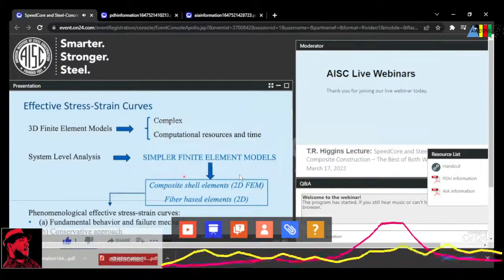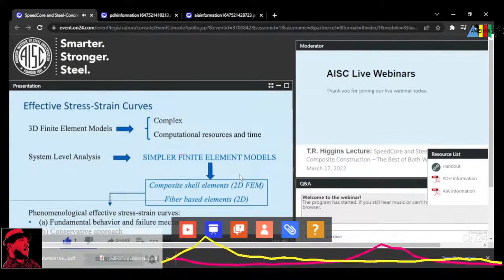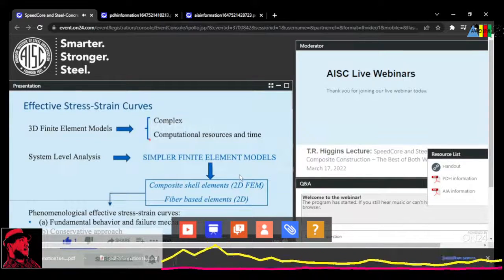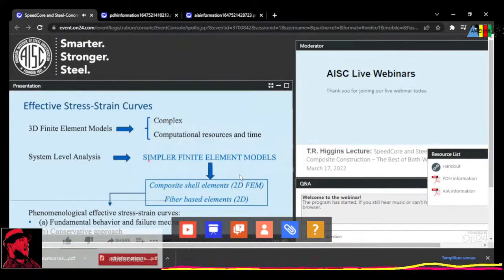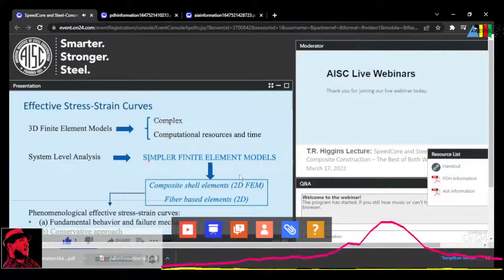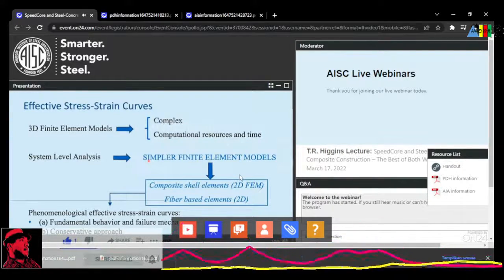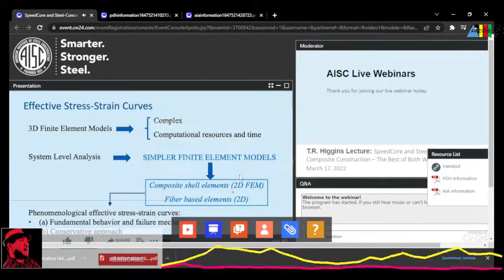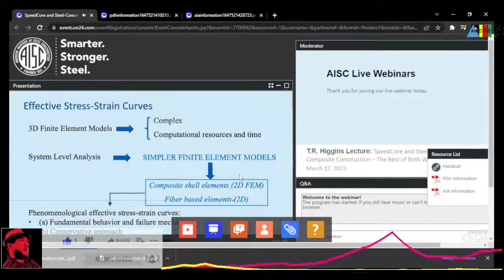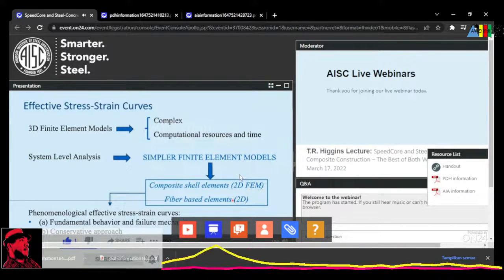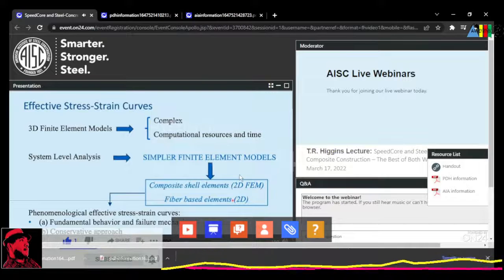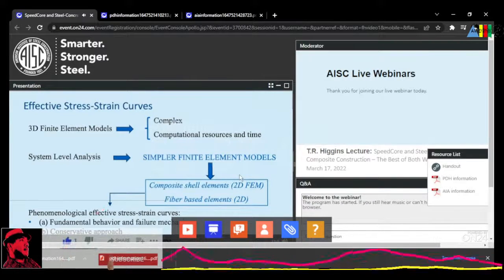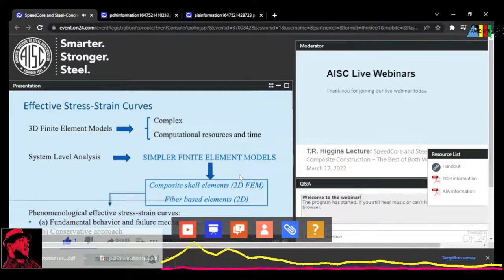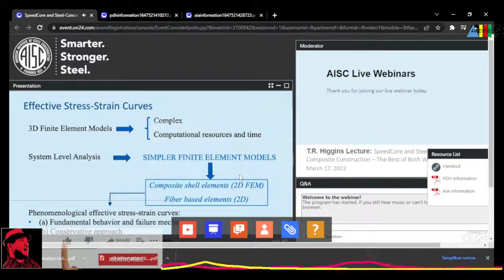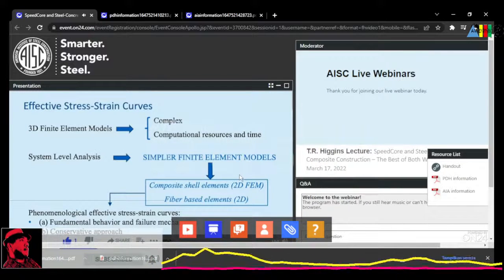However, the 3D finite element models are quite complex and time-consuming. They are good for evaluating local specimen behavior and failure. However, for system-level analysis, we need simpler 2D finite element models made from layered composite shell elements or 2D fiber element models. Both of these, however, cannot model some aspects of behavior directly. So we developed effective stress-strain curves to indirectly incorporate yielding, local buckling, confinement, etc. conservatively.